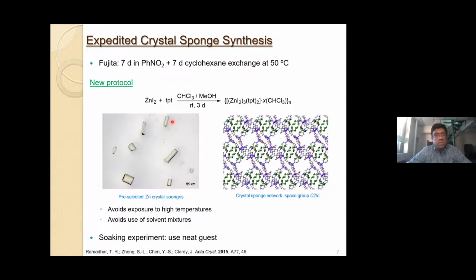So I was able to reduce the synthetic time from 2 weeks to 3 days, and it avoids exposing the crystals to high temperatures, which is important because higher temperatures can degrade crystallinity. And not only that, you avoid the use of solvent mixtures, because you can imagine if you're doing the refinement process and you have a molecule that is aromatic, there's still the potential to have residual cyclohexane inside of the crystalline sponge through the Fujita protocol. And it can be easy to confuse cyclohexane for benzene, especially if there's a lot of disorder.